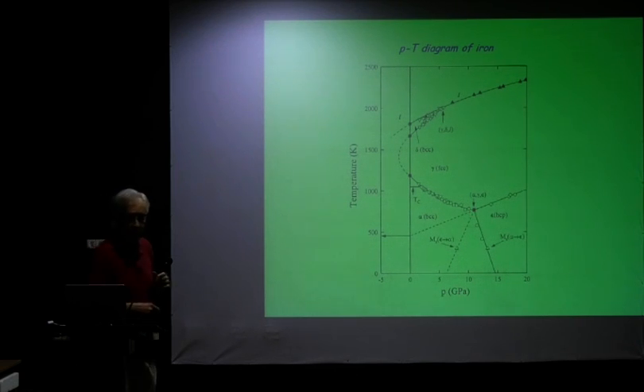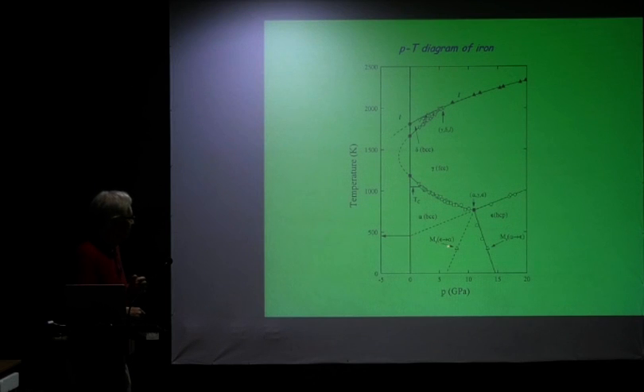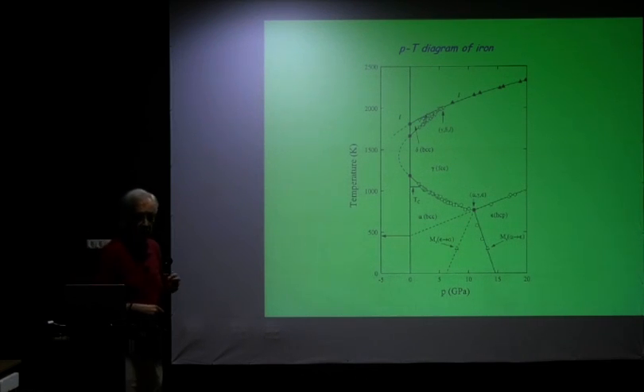If above a certain pressure, however, the gamma phase transforms to the so-called epsilon phase. The epsilon phase comes after delta because it was found after delta. The epsilon phase is hexagonal. So if you apply a high enough pressure, you come into the hexagonal state. Now, if you are at room temperature and apply pressure, you are in the body-centered cubic state, and then you cross a line at around 15 gigapascals, and then you come into the epsilon phase. If you want to return back into the alpha phase, there's this tremendous hysteresis here, and it's only when you come below this line over here that you get back into the alpha phase.